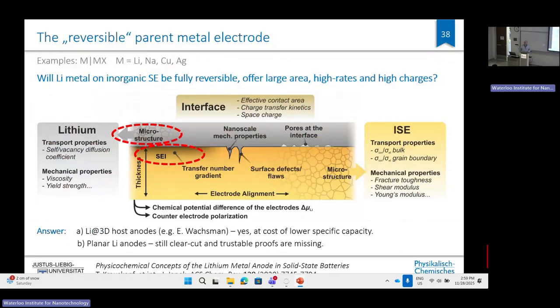That goes back in principle to theoretical predictions by Don Siegel from Austin in Texas, who predicted that if you have small-grained lithium, let's even assume nanocrystalline lithium, diffusion in the grain boundaries is much faster. And so the idea was that nanocrystalline lithium may have much better kinetic properties than large-grained lithium.